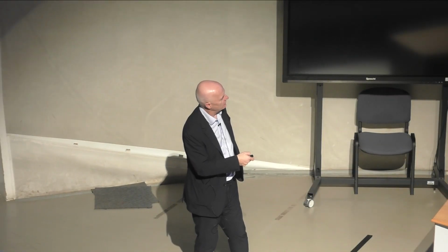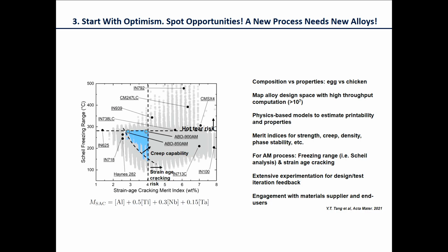So we had a very, very simple concept. If we want to put these alloys into the additive manufacturing machine, where the cooling rate is perhaps 10 to the 5 per second, there's a big risk of cracking at that kind of speed, then we need to limit the freezing range and we need to limit the strength. And that was all we did. That was the basic concept here, to design alloys in this region here.